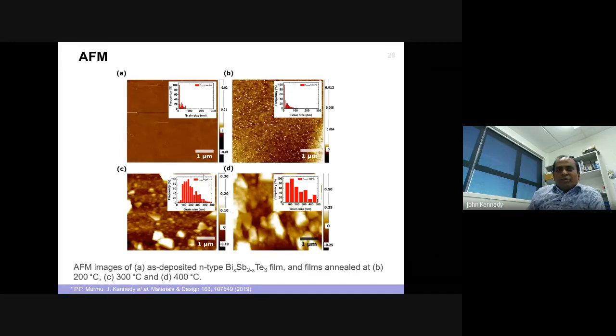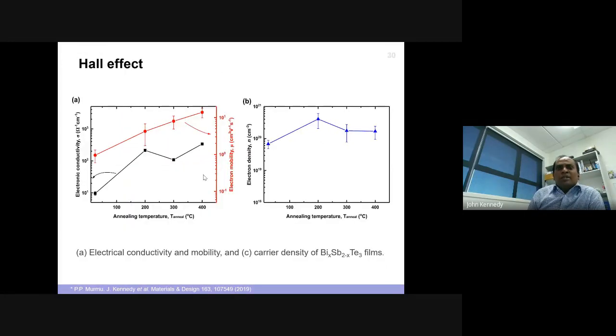So in net effect, so what? How does this relate to electrical conductivity? Because that's what matters for us. We did the Hall effect measurements, and as you can see, we are able to improve the electrical conductivity, depending on the annealing, from 10 to the power 1 to 10 to the power 3, which is a significant increase.